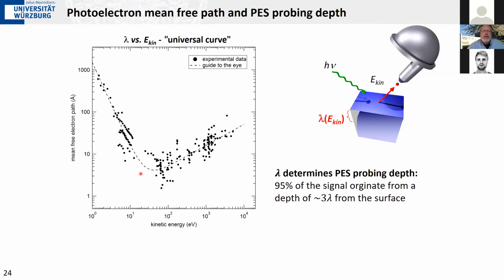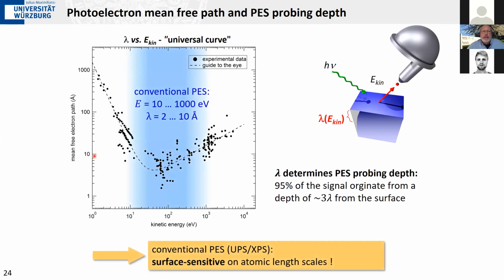And you can see that in the energy range that we have been discussing so far, so I was talking about photon energies of 20 to roughly 2000 electron volts, you are in this energy range here. That the mean-free path of the photoelectrons is rather low. It's only of the order of a few tenths or even less than 10 angstroms. These are atomic distances, and that means that for the energies that I just addressed, the photon energies and the resulting photoelectron energies, we only probe a relatively thin layer of just a few atoms thick or a few unit cells thick. So these are the numbers, and that means that photoemission, at least in this conventional way with the photon energies just mentioned, is a rather surface sensitive method. And that will, as we will see later on, be very important if you look at transition metal oxides.